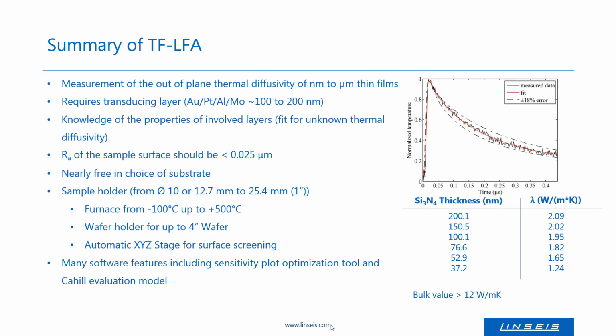The used measurement method requires a transducing layer of approximately 100 nanometers, as well as very smooth surfaces for the measurement. The big advantage is that it is an optical measurement and thus can cover a broad temperature range, and is nearly free in the choice of substrate.